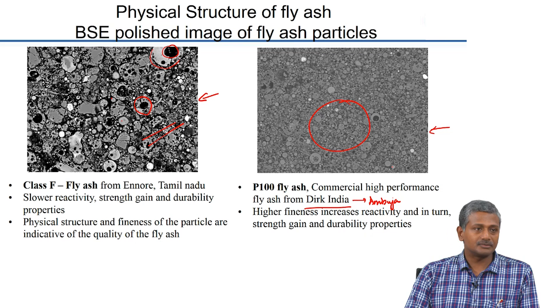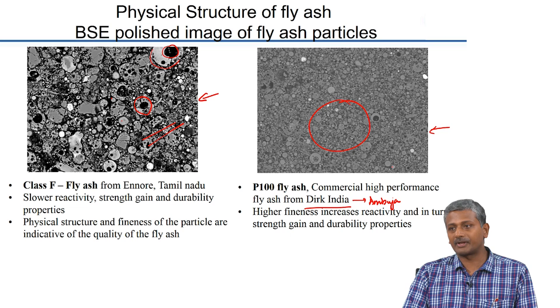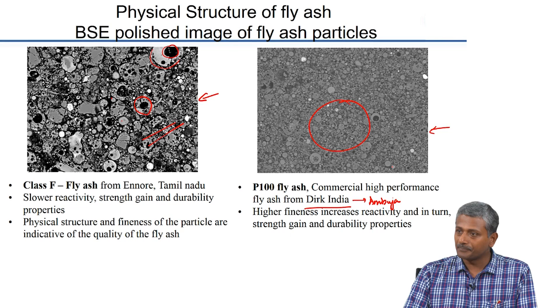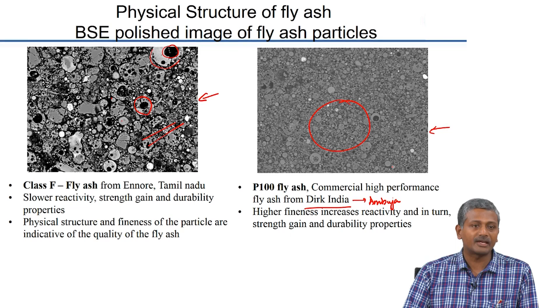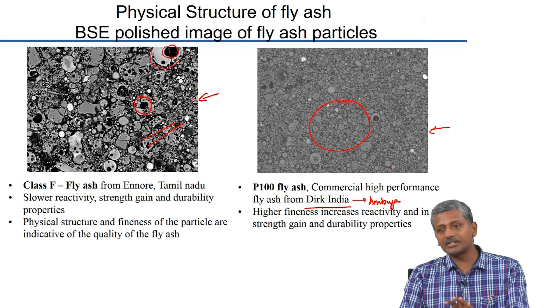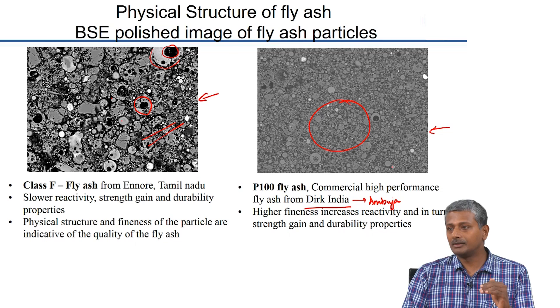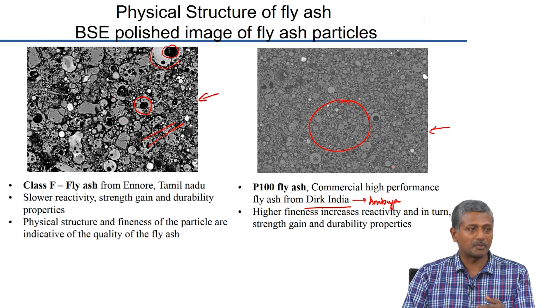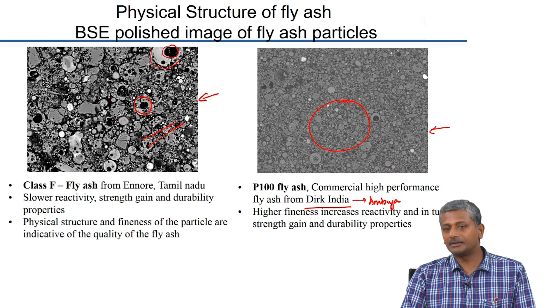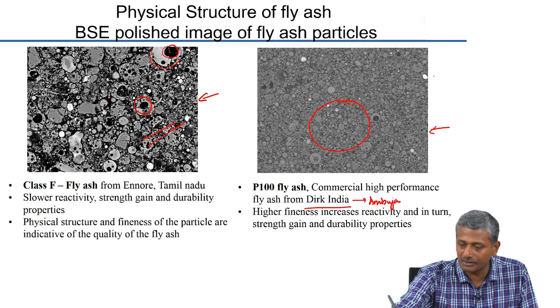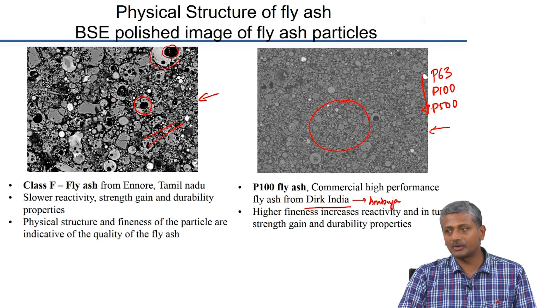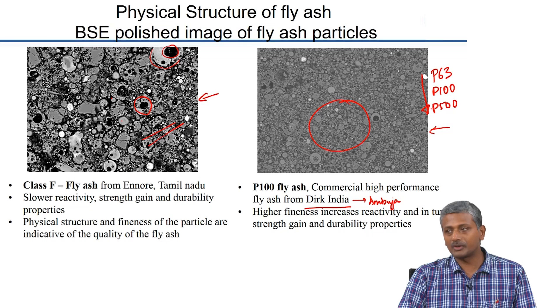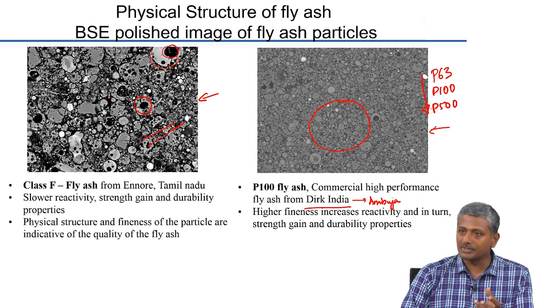Process fly ash is better for obtaining consistently good quality concrete. There is a business opportunity in collecting, processing and classifying fly ash by particle size. Dirk India sells different types — P63, P100 and P500 — with increasing levels of fineness. This enables concrete producers to use specific combinations for particular types of concrete. For example, a current lab project deals with production of high performance grouts intended to fill post-tensioning cable strands, where high fineness fly ash can be used as partial cement replacement to achieve flow over long distances into sheathing.